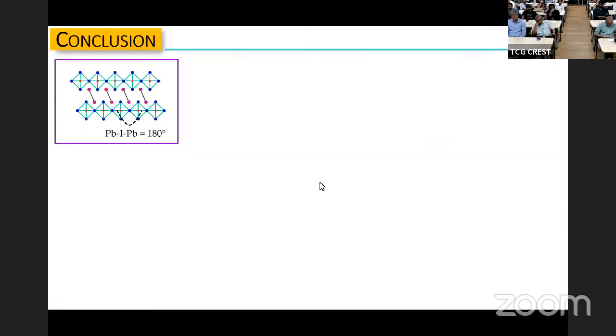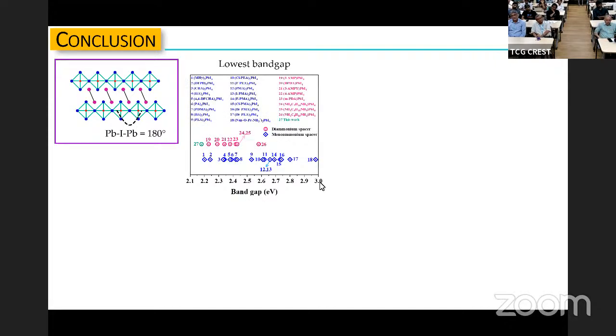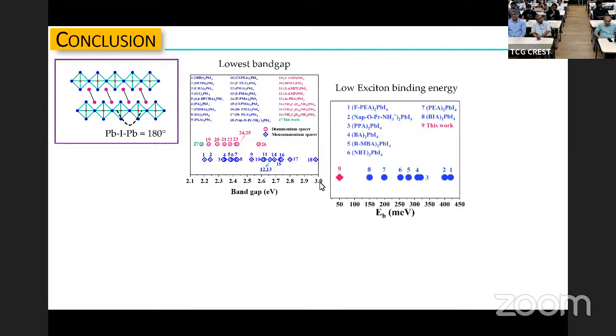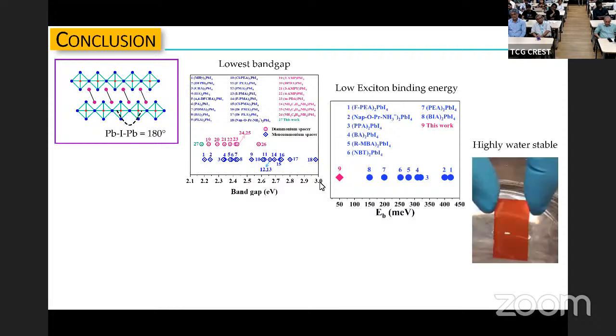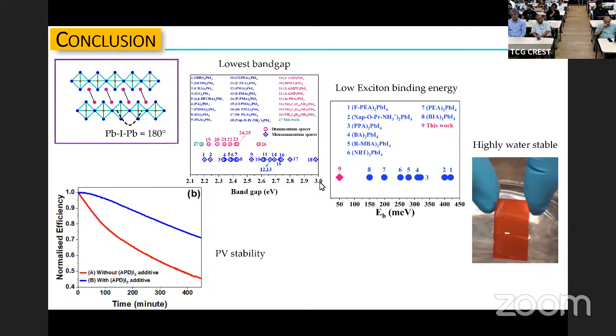So let me summarize this part of the talk by pointing out that I have shown you a very unique compound with a Pb-I-Pb angle of 180 degrees and explained why that comes about. And I've shown you that it shows the lowest band gap of all materials in this class, lowest excitonic binding energy, very high water stability, and also stability in a device structure.